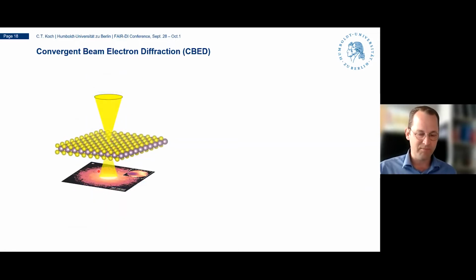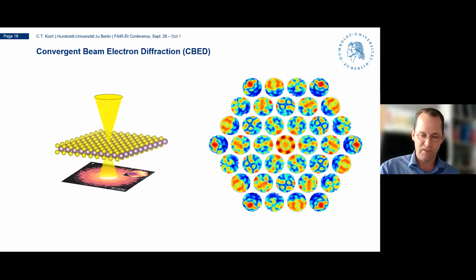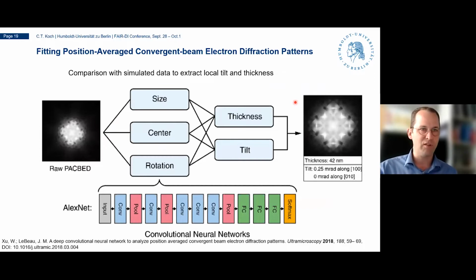Here's another example. This is when you shine in TEM an electron beam through a sample, you can collect the diffraction patterns. And the diffraction patterns, if you collect them in different ways, they may look, for example, like this. If your convergence angle is smaller than the inverse of the unit cell size, these disks don't overlap, and you get these beautiful patterns. And they contain a lot of information. But one thing that people want to extract from this is how thick the sample is. So you do a lot of simulations, and then you train an artificial neural network. These are position averaged convergent beam electron diffraction patterns. So you position average over basically one unit cell in your material, and you get these patterns, and you can easily compare that with simulations.